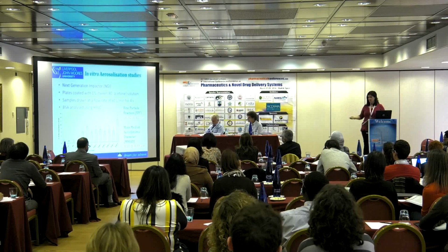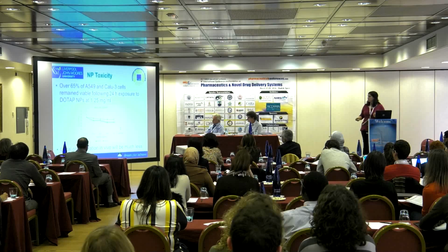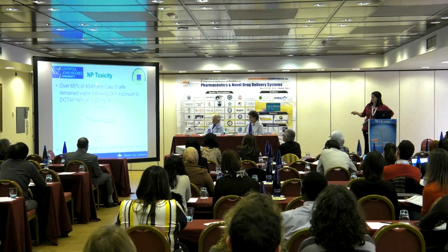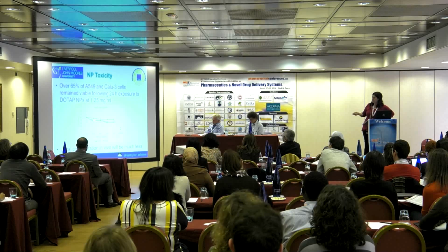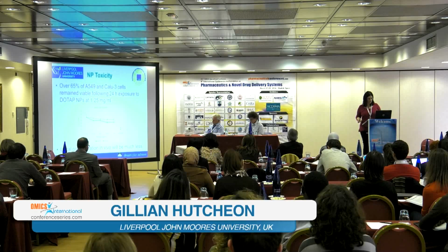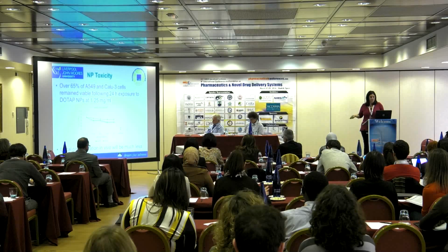We want to look at toxicity of the nanoparticles. When we use our nanoparticles without any DOTAP, we get very little toxicity with cells. Incorporating the DOTAP does give us some toxicity, and we've looked at this with lung cells, A549 or Calu-3. You can see that over 24 hours, we still have 65% viability. That doesn't look so good, but we have to remember that this is a far higher concentration than we will ever see locally within the lung. It's one of those issues. We need positively charged nanoparticles. They are more toxic than the negative.